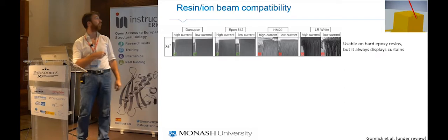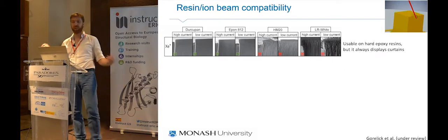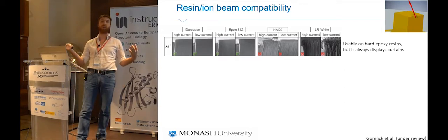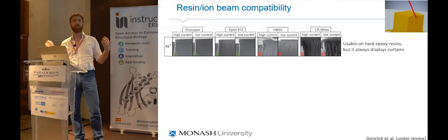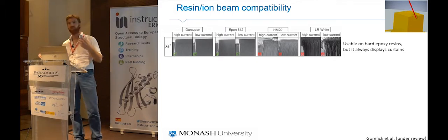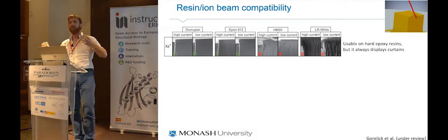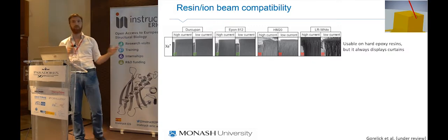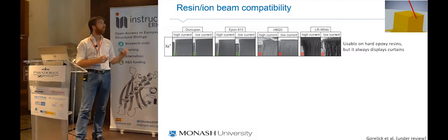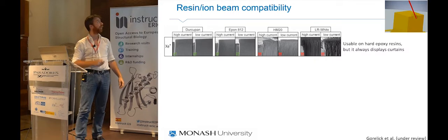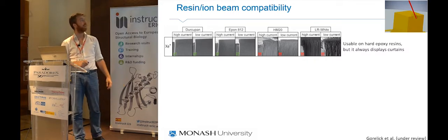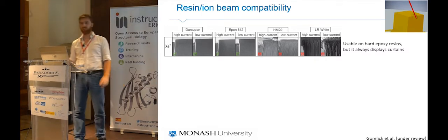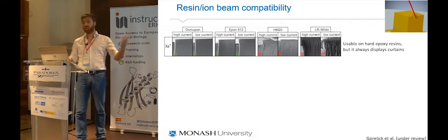We used xenon. Why did we use xenon? Because it's the heaviest plasma you can light up, and so it's very efficient in sputtering, and it's the only commercial gas. So everybody that has a plasma FIB will have a xenon FIB. Okay. So what we found out is that epoxy behaves okay, acrylic doesn't. So the xenon doesn't really work on acrylic resin.